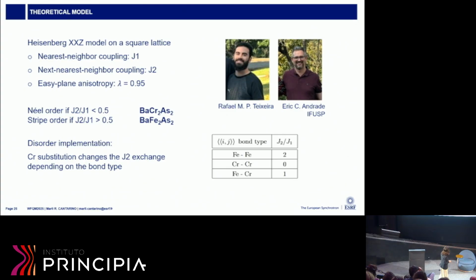And on one limit it will be Néel order, which is the case of barium chromium 2 arsenic 2, and on the other limit it will be a stripe order. To implement this on the system, the chromium substitution will change J2, so only the second neighbors will be changed.